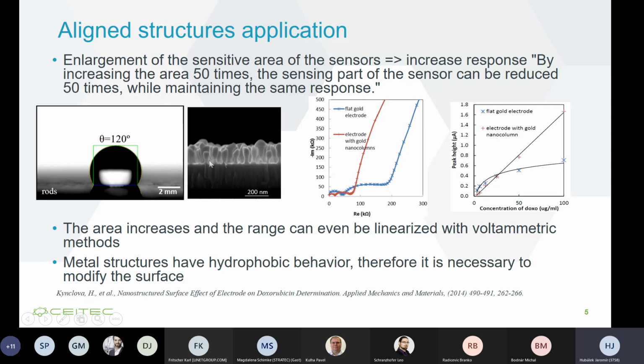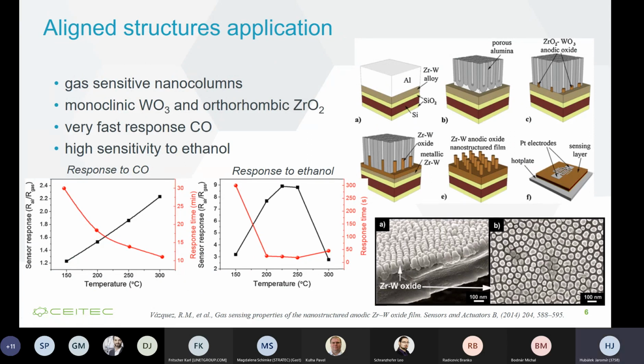But the hydrophobic or super hydrophobic properties of these structures have to be avoided in the measurement when liquid solutions are used. But this electrochemical way enables using this approach for biosensing, electrochemical biosensors especially. An easier way is to use this aligned nanostructure in gas sensing. Here we present that it's possible to anodically oxidize an alloy.